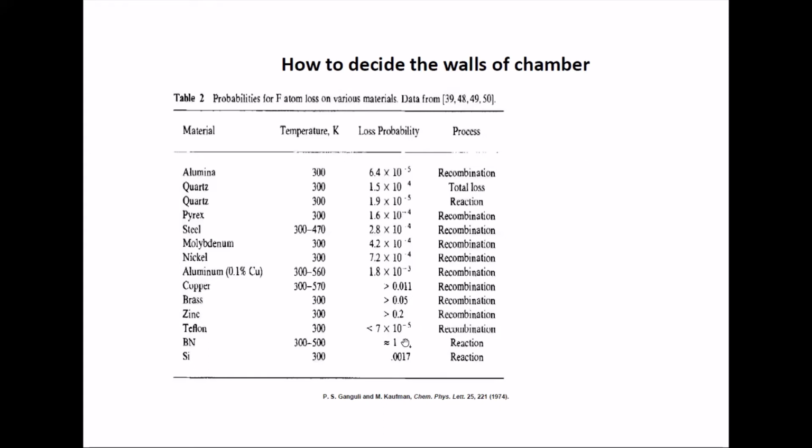There is almost a probability that it will form a reaction with the chamber. On the other hand, if you use alumina or quartz, the reaction probability, the loss probability, is very, very low, which will give you a longer lifetime of the chamber.